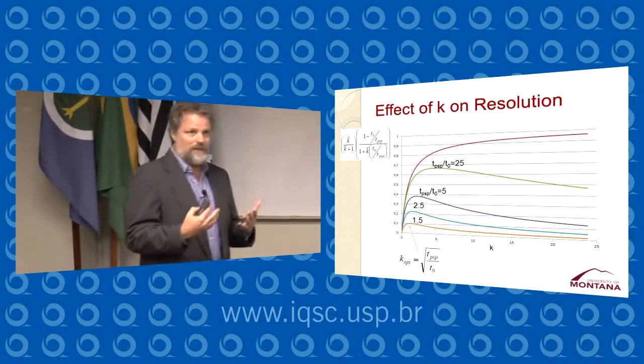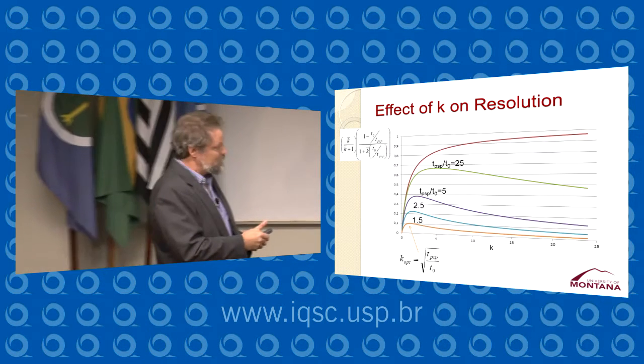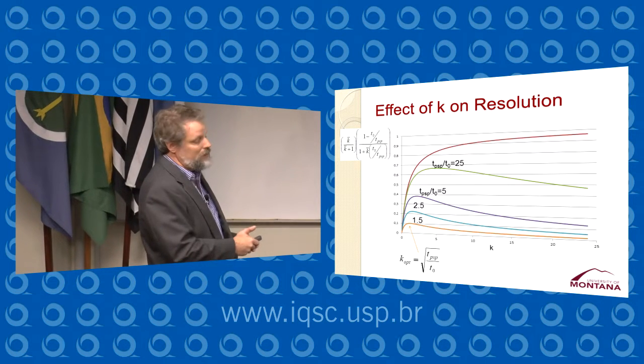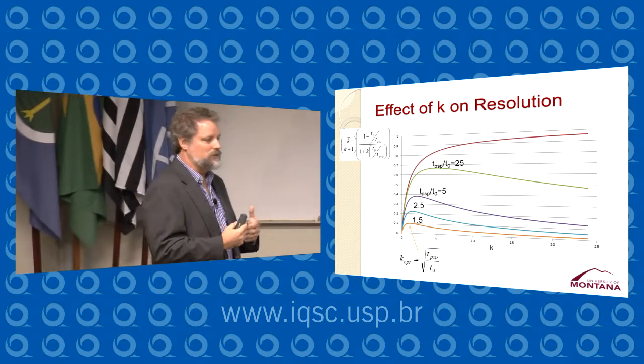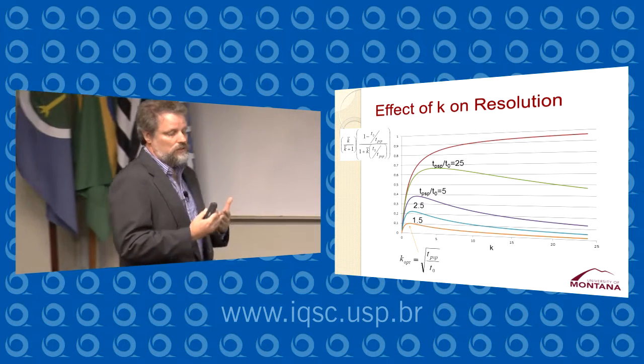And the other thing is that there is an optimal range for the retention factors. So we need to be able to adjust the conditions of the separation in order to optimize the retention factor to get the best possible resolution. And all of that leads to considerations for how you would develop a pseudostationary phase to give the best possible performance and the best possible separations in electrokinetic chromatography. So we're concerned about the aggregation properties. If we're going to use micelles like sodium dodecyl sulfate micelles, then we have to be concerned about the concentration at which they aggregate, because if we have a lot of excess surfactant in solution, we have a lot more current, and a lot more current leads to lower efficiency.